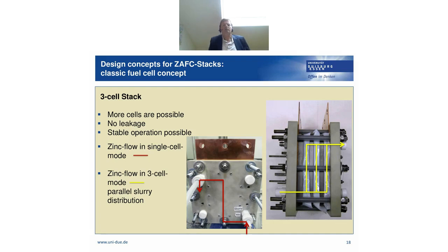Then we built a 3-cell stack with the help of these anodic and cathodic flow fields, and we did not see any leakage and also had a stable operation. And here's depicted how the zinc flows in the single cell mode. Here is the red line with slurry in and slurry out, and on the right photo you see the way the zinc flows through the 3-cell short stack. You can say it's a parallel slurry distribution.